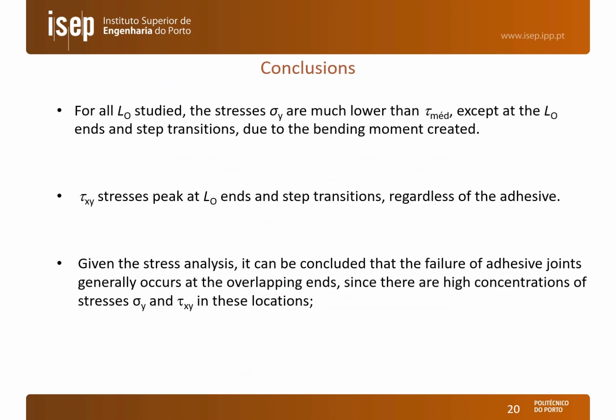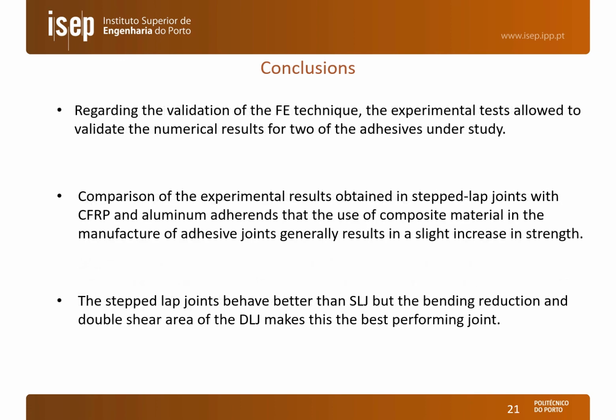To conclude, regarding the stresses, typically peel stresses are much lower than the average shear stress, except at step edges. Shear stresses peak at the overlap and step transition edges, regardless of the adhesive, and we can see that we have high stress concentrations that increase with the overlap length, which tends to affect the results. The CZM technique was validated. Good results were obtained, especially for the two Araldite adhesives, although for the Sikaforce the results were not so good, but this was already addressed, the explanation.